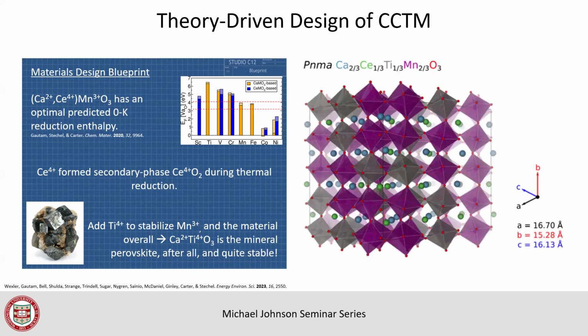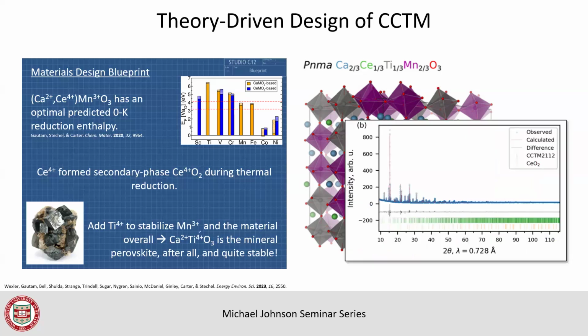Here's what it looks like. This was a model we came up with. So here the green are cerium. Those green circles are cerium. The blue is calcium. The gray octahedra are titanium surrounded by 6 oxygen. And the purple are going to be manganese surrounded by 6 oxygen. You can see diversity of color. It's basically like kind of a random mixture of these species on their respective sites. We created this model. It appeared to be stable.